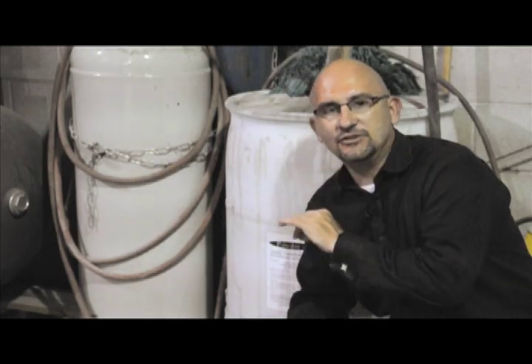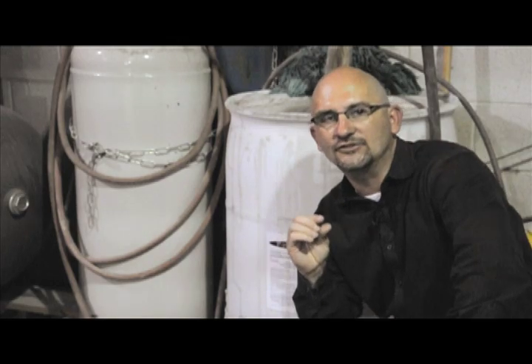Multi-metal is the kicker. You're asking if we use a different chemical for steel and aluminum? Not actually, not with this system we don't. This is used in most pre-treatment, closed loop type pre-treatment stations, 3-stage washers, steam units, things of that nature. We say multi-metal because that lets the engineers at the chemical company know to put a little bit of fluoride in when they're creating the chemical so it will help etch the aluminum. Regular phosphates won't do that. So we need that little bit of fluoride in order to etch the aluminum so the powder's got something to bite to. Hope that helped you, and we'll see you next time.